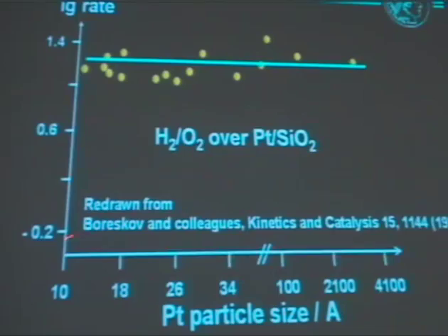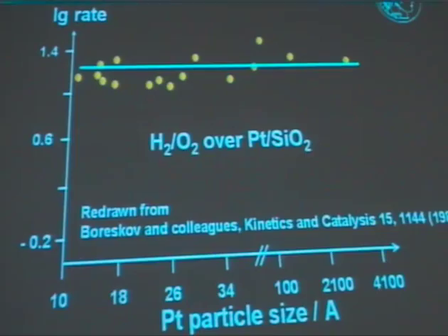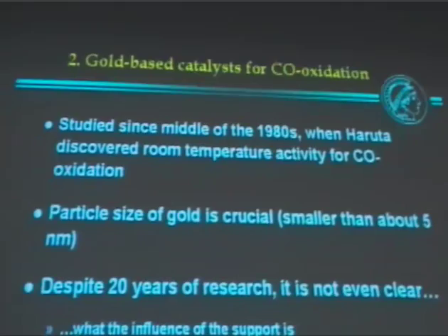So for this reaction, it was really settled, there is no question about it. But there is another reaction of extremely high current interest in the literature, but this is clearly not the case, and that is the CO oxidation of gold catalyst, where it's pretty clear that you need small gold particles, preferably in the range of 5 nanometers, to get catalytic activity in CO oxidation, and I would say unprecedentedly high catalytic activity. That was discovered by Haruta in the middle of the 80s, when he really found, if you make gold